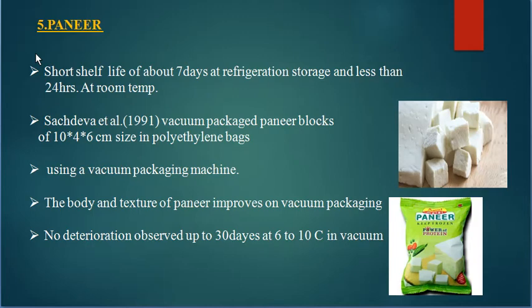Sachdeva et al., in 1991, reported that vacuum packed paneer blocks of 10 by 4 by 6 centimeter size packed in polyethylene bags, with vacuum packaging of paneer at 6 to 10 degrees Celsius, increased the shelf life up to 30 days, and also the body and texture of paneer was improved in vacuum packaging.